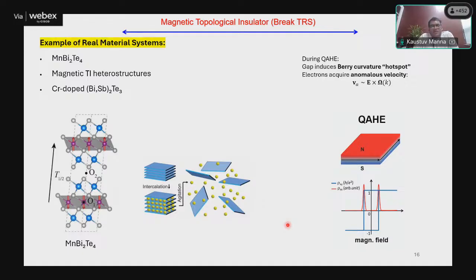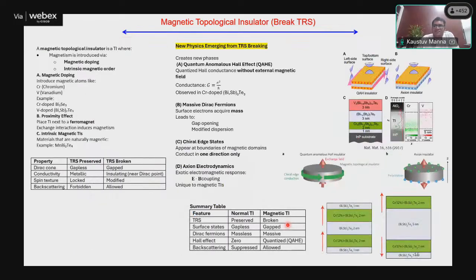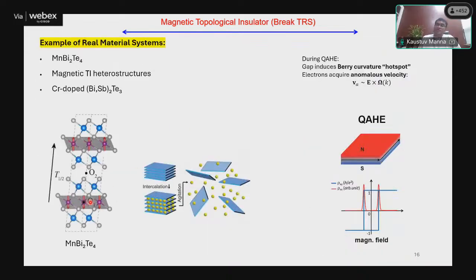So manganese bismuth telluride, as I said, is one of the rarest examples where you can observe these effects in the same compound. If you want to observe this effect, you need a very sophisticated experiment, like using MBE, where you make layer by layer deposition and build the device where you have to control the composition. As you can see, the composition is so complex and controlling is very, very tough. Not everyone can do it. However, in MnBi2Te4, we don't need to do any compositional variation. Nature provides it for us.